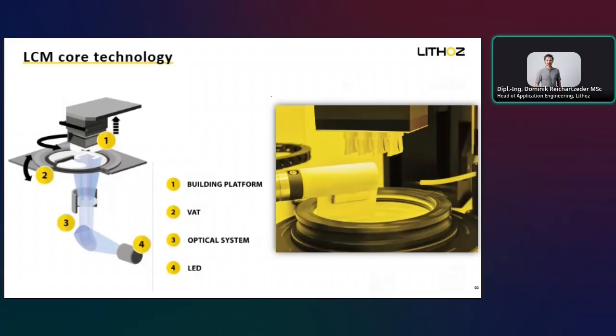The core unit of our printers consists of a LED light source exposing blue light onto the optical system, which projects a defined 2D picture onto the vat. The vat is filled with a photoreactive ceramic suspension called slurry. This liquid slurry cures when exposed to the blue light, turning into a solid polymer filled with ceramic particles. The first layer attaches to the build platform onto which the entire part is being printed layer by layer. We use layer thicknesses from 10 to 100 micrometers and pixel size from 10 to 75 micrometers, depending on the 3D printer and, of course, on the requirements of the application.